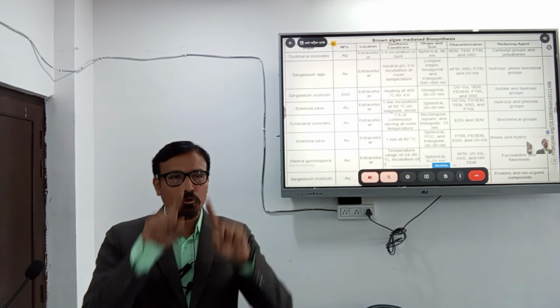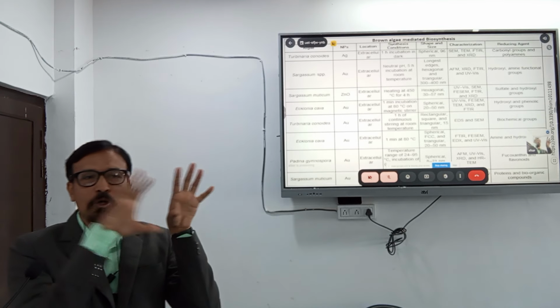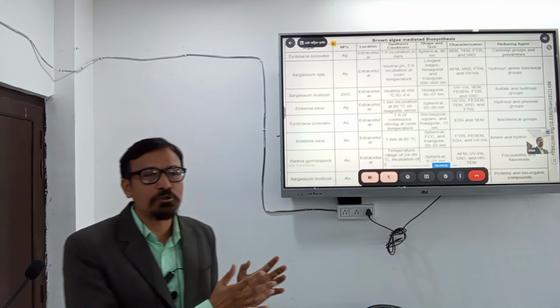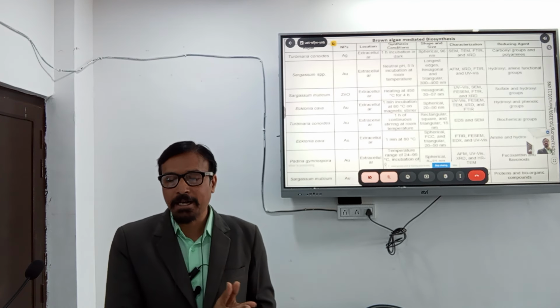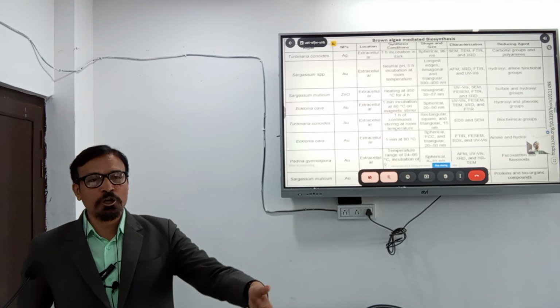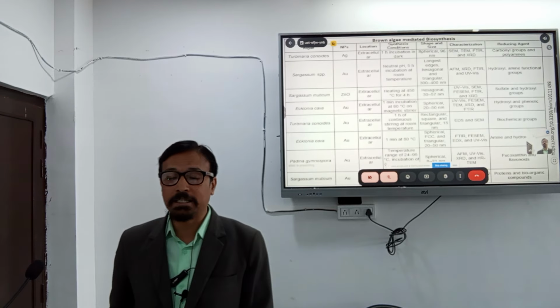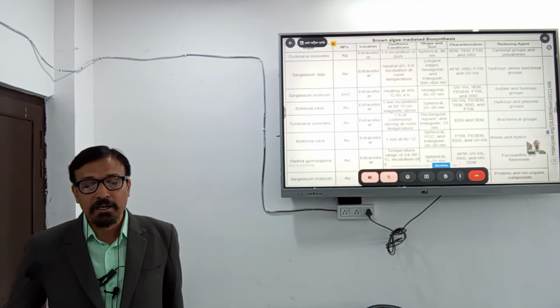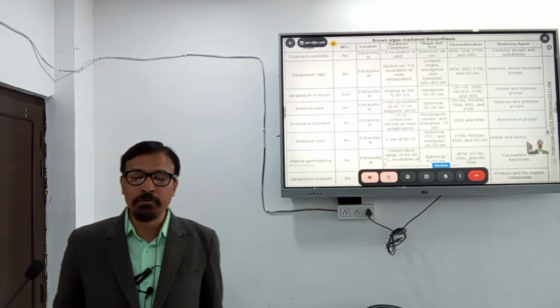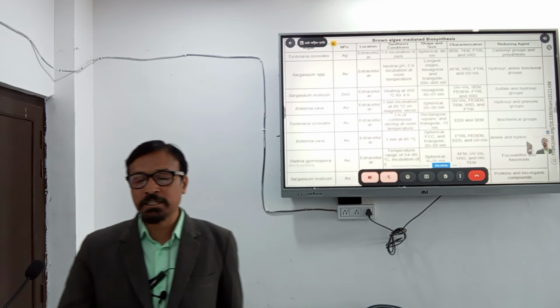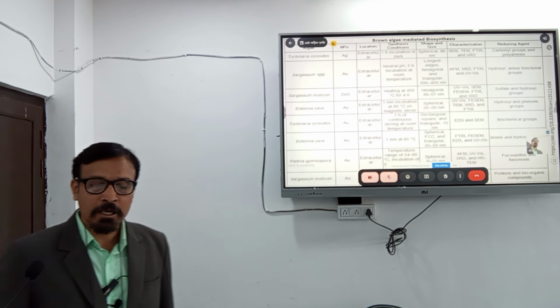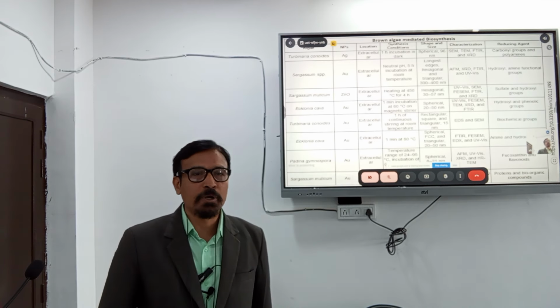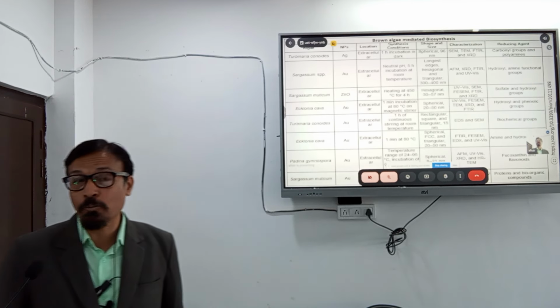And the triangular shape of the nanoparticles also can be obtained with the size of 20 to 50 nanometers. And the characterization of these gold nanoparticles can be done with FTIR, FESEM, EDS, and UV-vis, and these are the reducing agents, amines and hydroxyl groups, which are ultimately responsible for the synthesis of the nanoparticles.